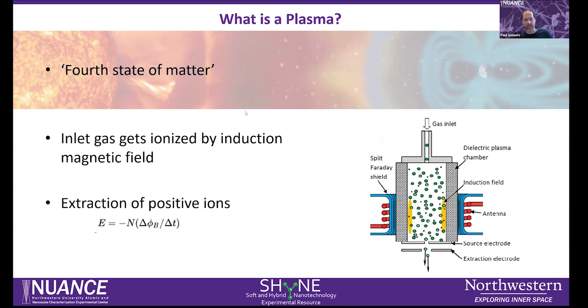For example, in space we have black holes that have plasma, and comet tails that have plasma in them, but we can also induce a plasma in the lab. So what happens in a plasma focused ion beam? Basically, we have a gas that's let into a dielectric chamber, and once we apply a magnetic field through the antenna coils, you get a magnetic induction field, producing a soup of negatively charged electrons and positively charged ions. Then you can extract the positively charged ions via an extraction electrode.